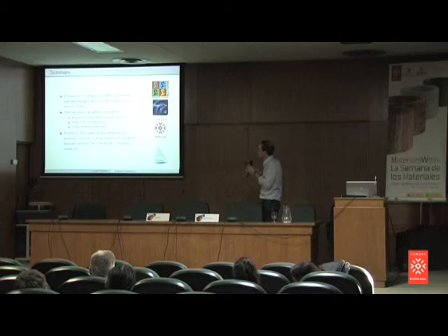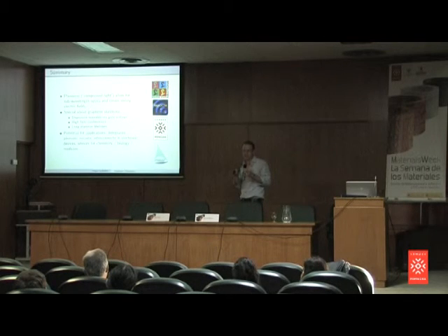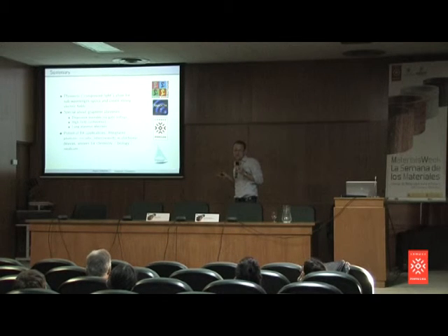And it is certainly a good idea to use graphene for plasmonics. The biggest advantage of graphene is the tunability of the plasmon dispersion, simply by applying a gate voltage. There are other possibilities. You can put graphene on a different substrate material, then you also get a different plasmon dispersion. I haven't even talked about that. And, well, the high carrier mobilities, which give long-lived plasmons.